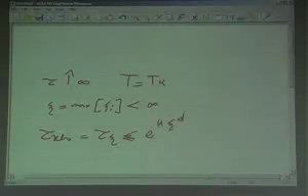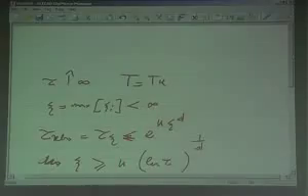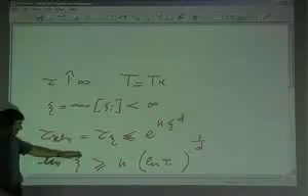Yeah, as I said, I don't need it, actually. It was just for the purpose of the proof. So I agree with you. It means that I get a bound, which is that psi should be larger or equal than a constant times log of tau to the power 1 over d. And I don't care whether tau diverges or not. I agree, it was just for simplicity. So that's the bound, and so you see, the length scale increases with the time scale.